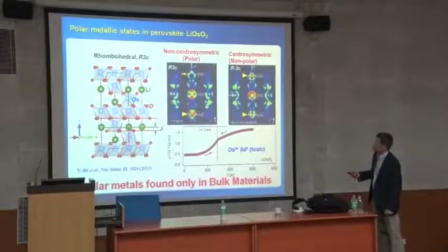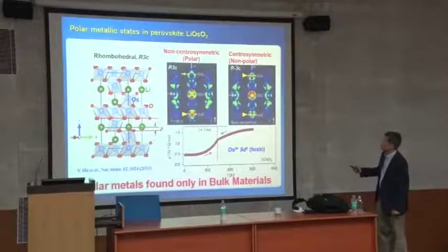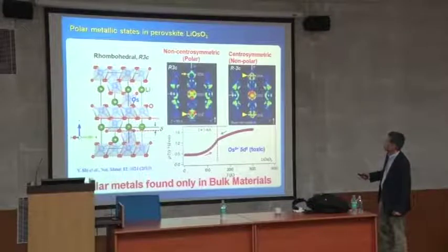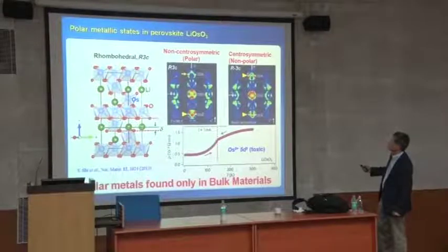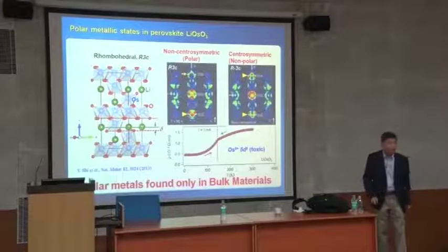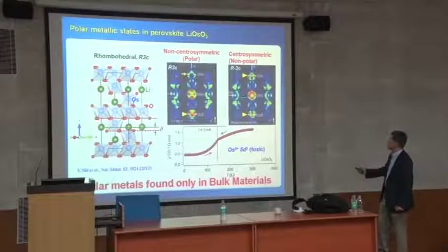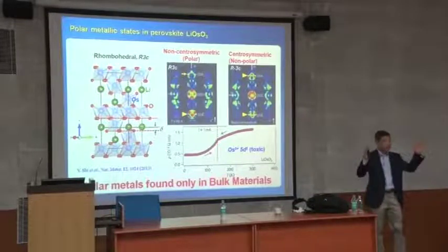And then, we have a complex way, because osmium is a toxic material and you have to be very careful. Lithium osmate has a rhombohedral crystal structure, and this is the convergent beam diffraction pattern, and it shows that it is a non-centrosymmetric case, okay? Non-centrosymmetric, polar, and this pattern and that pattern are not the same, right? You can see this one and that one. But in a centrosymmetric non-polar system, the patterns are mirror symmetric. Can you see that? Because this is a mirror plane, when you divide these two, this image and that image are exact mirror images. So a mirror image means centrosymmetric.